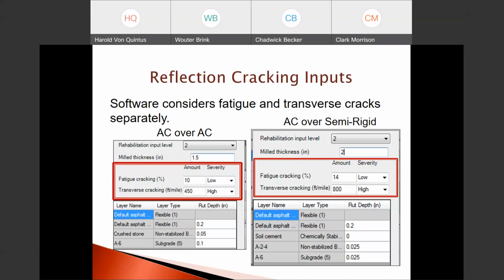As shown in this example, we have 10% fatigue cracking, percent total lane area, that has a low severity. We have, as shown in the example on the left, 450 feet per mile, but those were classified as high severity. On the right, the input, we have a mill thickness of 2 inches. We have fatigue cracking of 14% total lane area of a low severity, and this is an AC over a semi-rigid pavement. And then the transverse cracking is about 800 feet per mile, and that's been classified as having a high crack severity. So those are entered, and the reason the severity level is entered, because this is for rehabilitation input level 2 for both AC over AC and AC over semi-rigid.